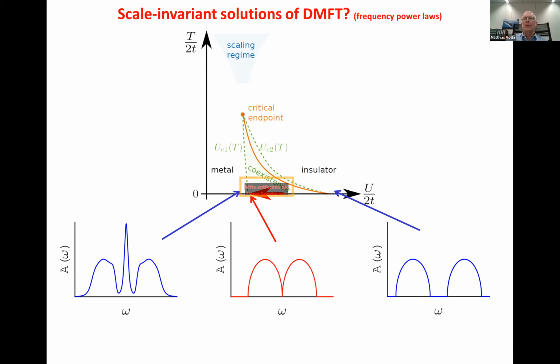The interesting thing is, if it occurs, it's in the insulator in the regime where it's only metastable, because this is on the left-hand side of the coexistence line in the phase diagram. In this regime, the metal is actually the thermodynamically stable phase, but the metal cannot develop a power law. It cannot become critical, but the insulator can.